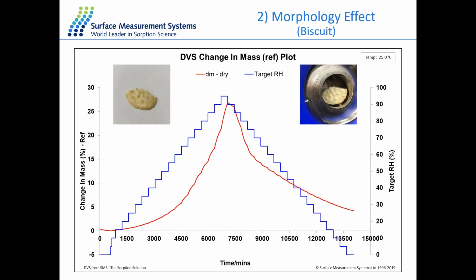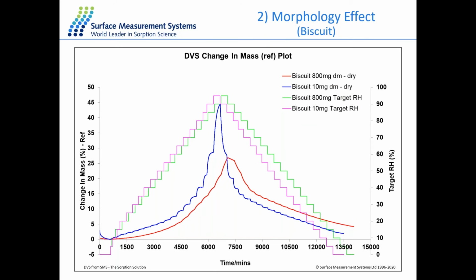So this set of data is basically a set of non-equilibrium data with the maximum stage time for each of the stages. And what we can improve for this method is we can increase the maximum stage time. But in this case, the experiment will probably take forever to complete. So we just perform another experiment with the same method, but smaller sample mass, which is about 10 milligram.